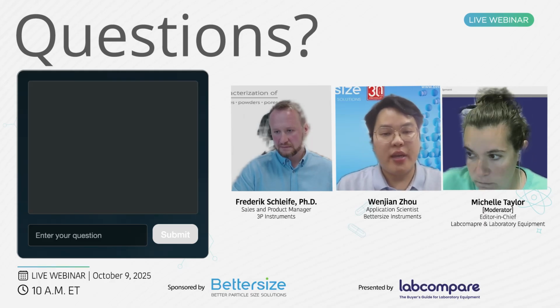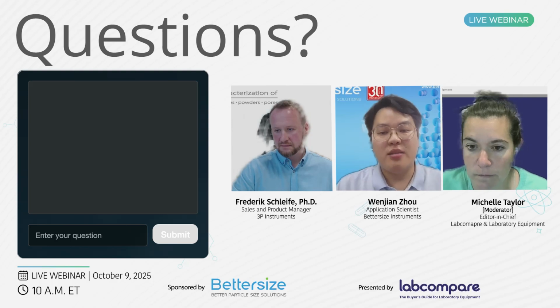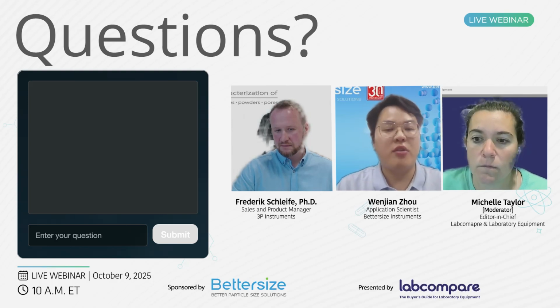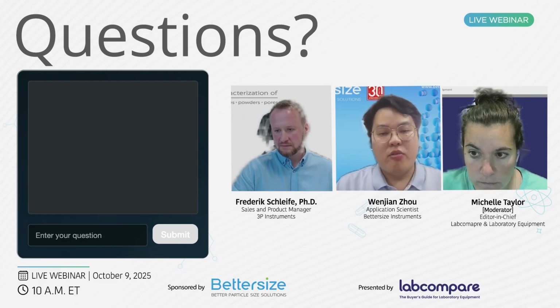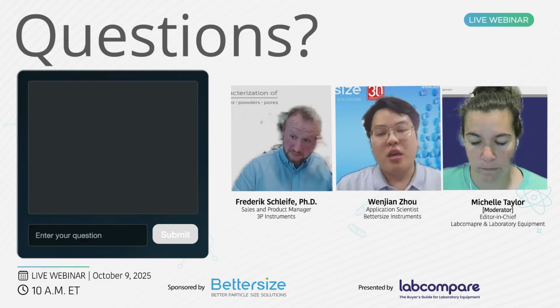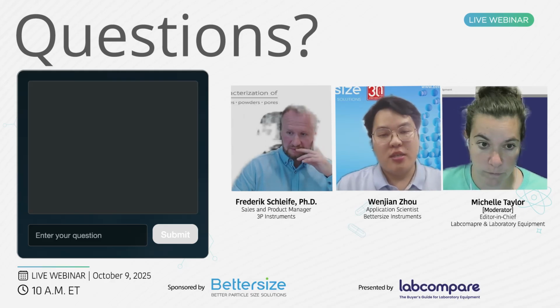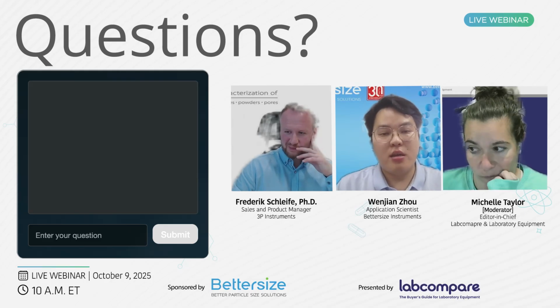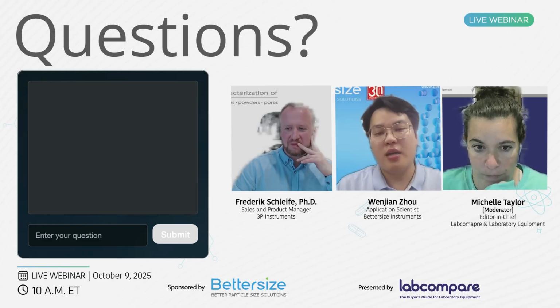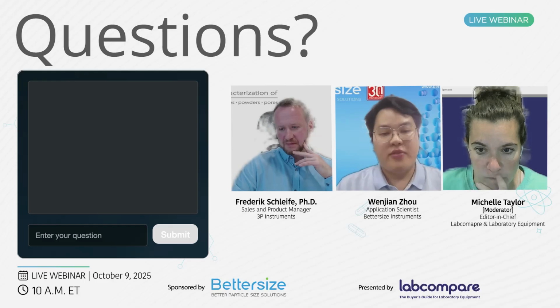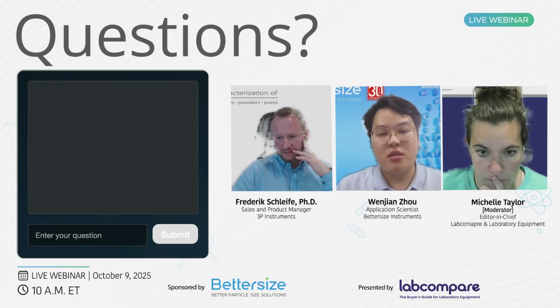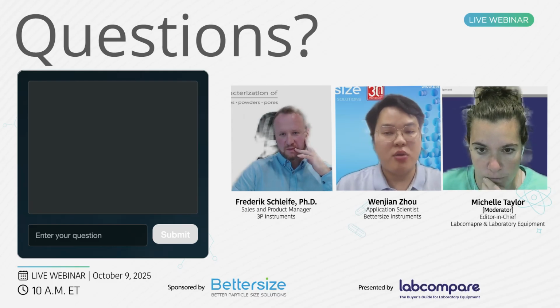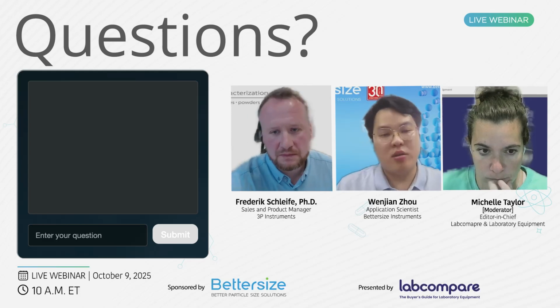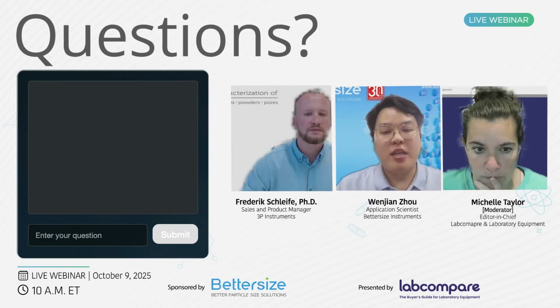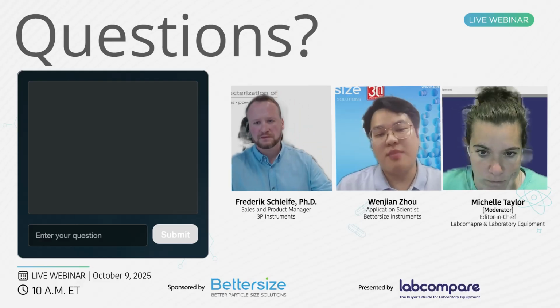For applications requiring high precision results, helium is generally considered the best choice due to its combination of low reactivity and superior penetration capability. However, for regular lab measurements, nitrogen is also a cost effective and chemically stable option. For non-porous samples or regular ceramic powders, the difference in measured results when using different carrier gases, for example helium, nitrogen, or carbon dioxide, is almost nil. We need to choose the appropriate gas according to our demands.